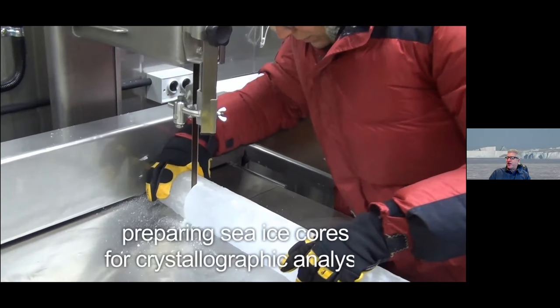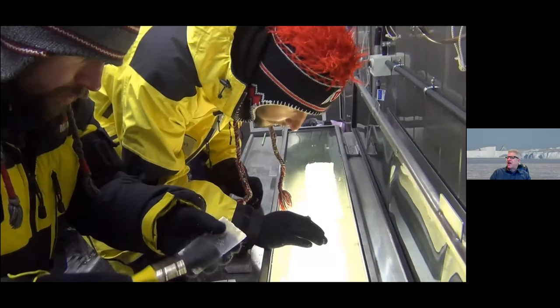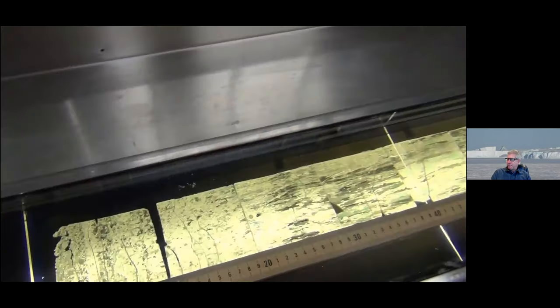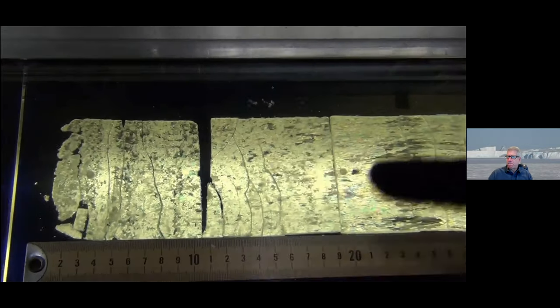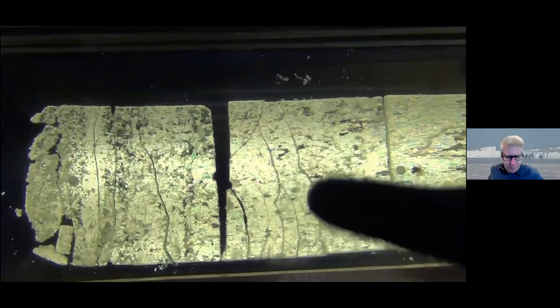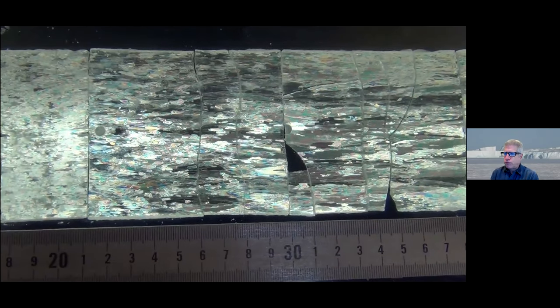This is working in the freezer, looking for crystallographic analysis. The top of the ice, which you can see these sort of round crystal grains. Then there's a transition at about 20 centimeters where we see it still looking fairly granular or like snow ice, but we start to see it turn into columnar ice.